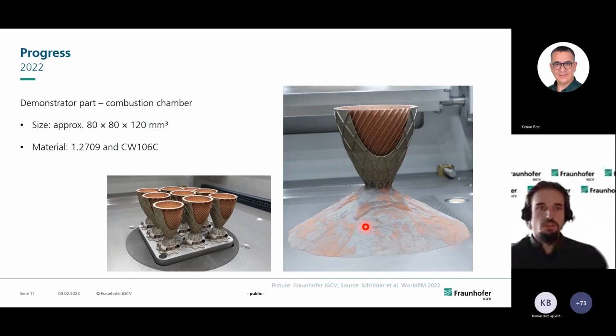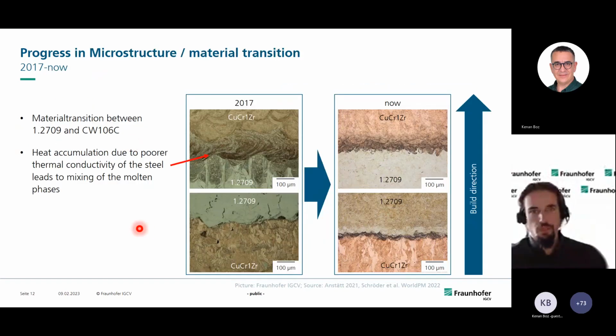Then let's move on to the progress in microstructure and the material transition. Here we made huge progress over the last years. You can see when we were building copper chrome zircon onto the tool steel, we got heat accumulation because the tool steel has a poorer thermal conductivity. So here the molten phases are mixing within the process. Vice versa, it's not that bad, as copper chrome zircon is quite a good heat sink. That's why it's used. And by now, with adapted path planning strategies for the laser, we managed to get a rather discrete material transition, as you can see here, and now in both ways.